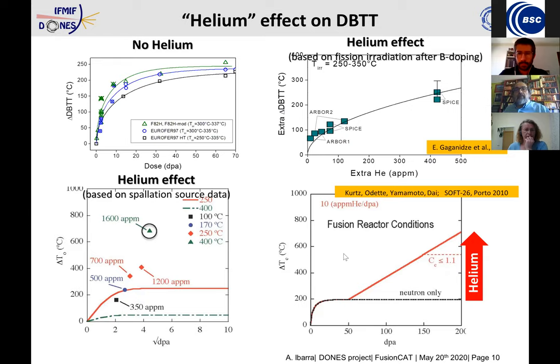The problem that we have is that these experiments are not fully relevant for the fusion case, because neither the boron dopant nor the spallation source are the proper experiments. They are not fully equivalent to a fusion one. So it is mandatory to have a better knowledge of the behavior of the material, and to do this we need a fusion-like neutron source. The important thing about this shift is that the design window that we have to use the material will be decreased.